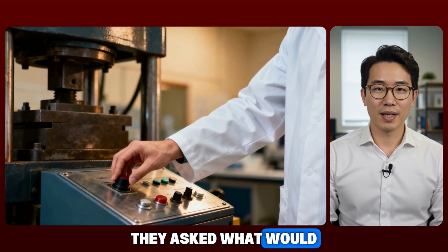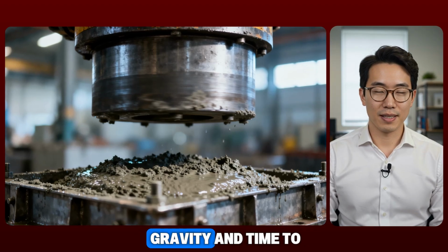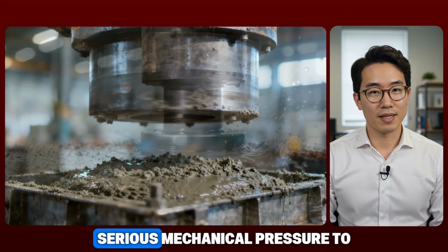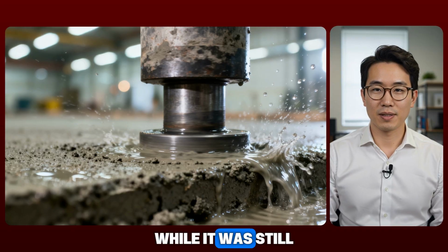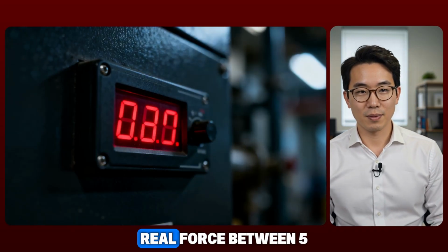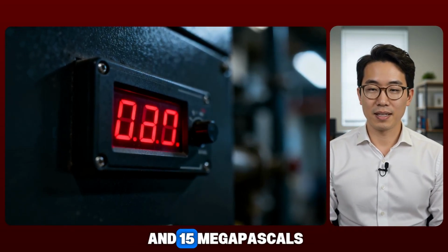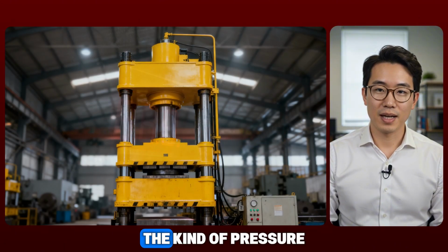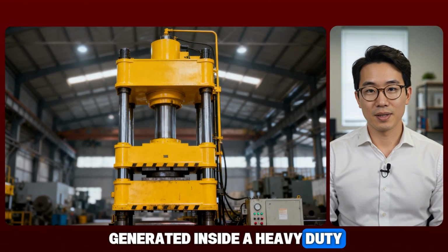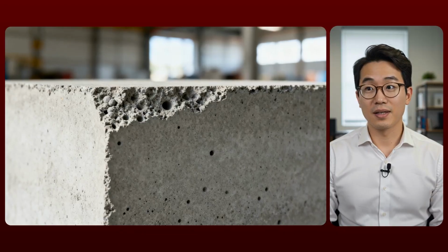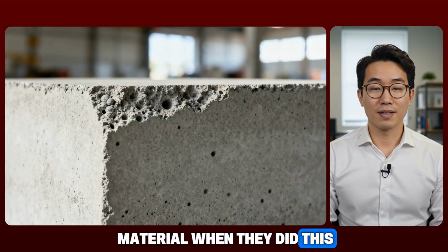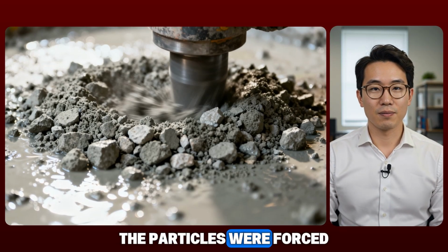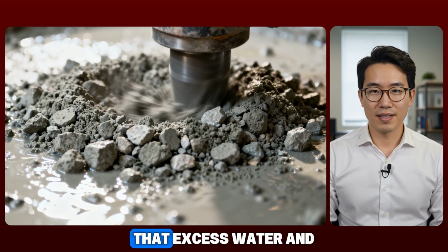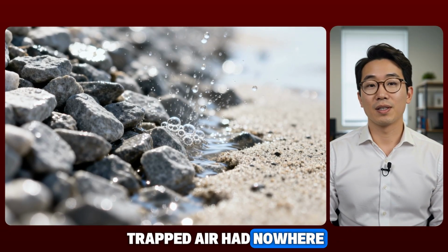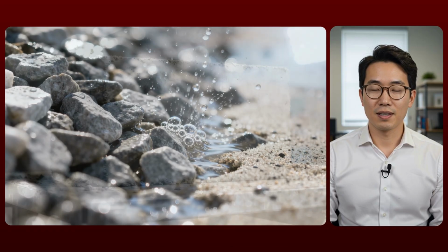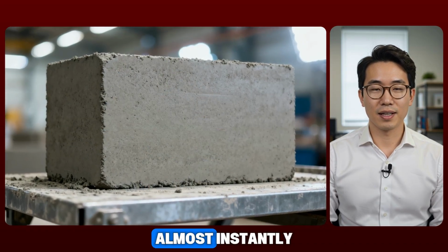They asked what would happen if, instead of waiting for gravity and time to do the work, you applied serious mechanical pressure to fresh concrete while it was still wet. Not a gentle squeeze, real force, between 5 and 15 megapascals, which is roughly the kind of pressure generated inside a heavy-duty industrial hydraulic press. What happened inside the material when they did this was dramatic. The particles were forced together so tightly and so quickly that excess water and trapped air had nowhere to go. They were squeezed out. The concrete became dramatically denser almost instantly.